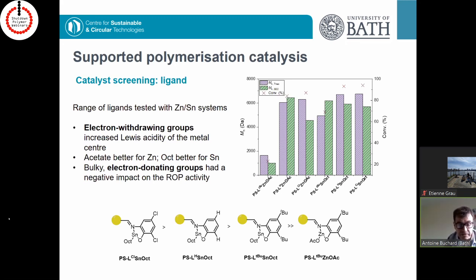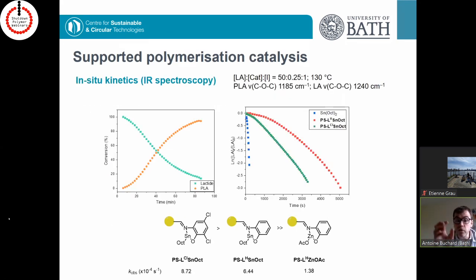clearly showing some good effect in terms of the activity. And we could also see an effect of the carboxylate groups. We could see the acetate was much better for zinc, whereas the octanoate, or strictly speaking, the 2-ethylhexanoate co-ligand, was actually better for tin. However, bulky electron donating groups, such as the tert-butyl, for example, didn't have a good impact on the activity. So we have located two good metals. We had an idea of what type of ligands to use, but now we wanted to know more.